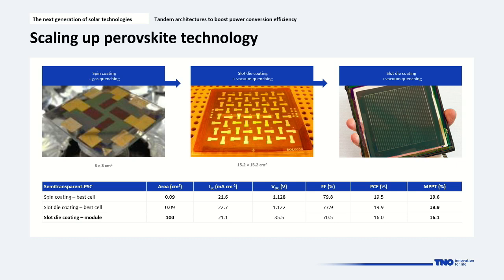And what we see when we do this transfer is that the efficiency of the device remains the same, in the range of 20%. So we accomplished the first step. The second step is that we build up what we call the mini module. On 100 square centimeters, we have a monolithic interconnection of different cells, and we get an efficiency for our device of 16%. Again, for a semi-transparent device, this is one of the highest worldwide.